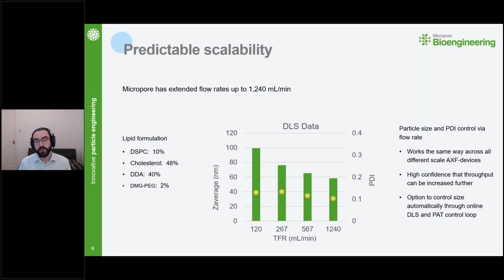Additionally, because we can run all of this continuously, it can function very well with inline DLS measurements that you can attach in via a control loop, and that can give you that control over the size. We're demonstrating control over the size by controlling the flow rate here. So you can imagine if you're continuously monitoring that in line, you'd like your size to be smaller, you can adjust the flow rates as needed.